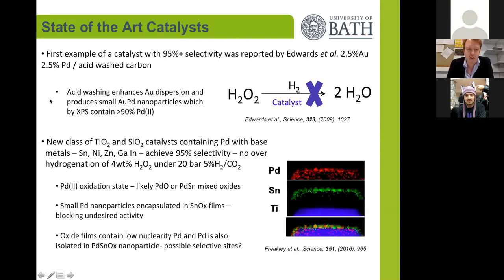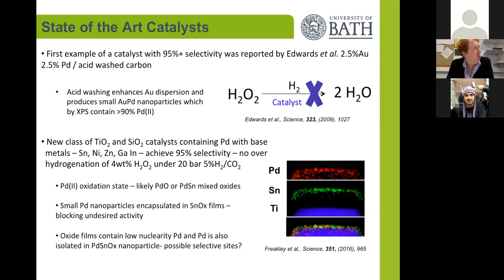This was the first example of a catalyst showing this unprecedented selectivity. Looking at the structural features, we know that the particles contain a lot of gold, so there's a very good dispersion. There are no very small palladium-only particles, and most of the palladium was present as Pd²⁺ in the catalyst.